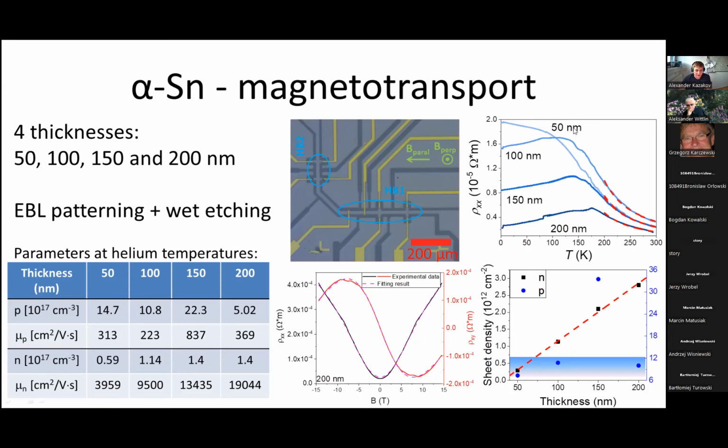The resistance grows with cooling down, and that is usually explained as depopulation of this L-point pocket, which is lying higher than the edge of the conduction band. At low temperature, we saw that resistance does not change very much with temperature, but the trend depends on the thickness of the film.